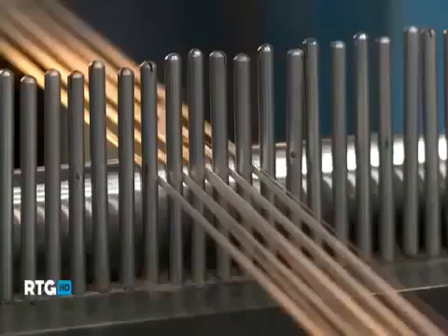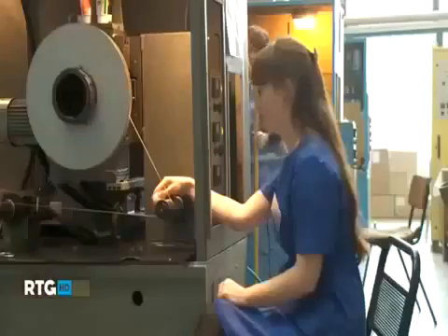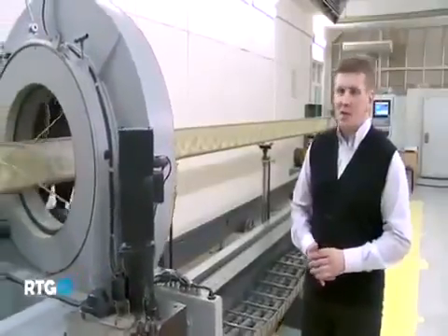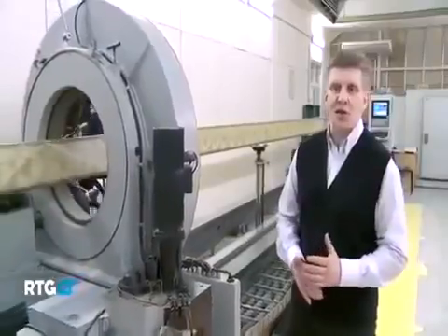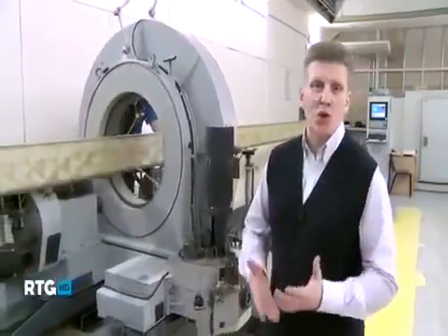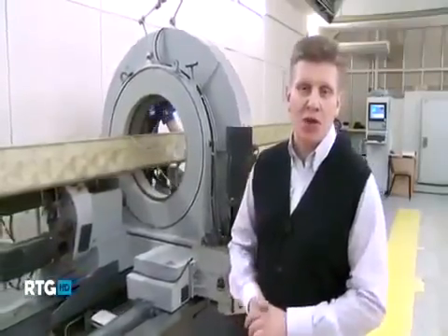First of all, 200 of them are glued together in a row, creating fiberglass ribbons. And then, with a machine, these ribbons are placed together crosswise to create the form. To make the longeron, the machine has to make 144 runs and use almost 3,000 kilometers of fiberglass filaments that are glued together into strips. These strips make the longeron more durable and stop it from shattering when it's hit by a bullet or a shell.